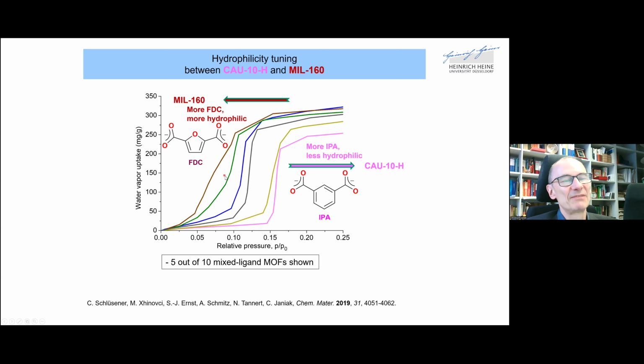Now if we partially replace furan dicarboxylate with isophthalate, we become a little bit more hydrophobic, and from the other direction we become a little bit more hydrophilic. These are 5 out of 10 modifications we have done with the mixed linker unit, and thereby this water uptake range can be adjusted. It may seem like a little game and not really so relevant, but for the technological application, such fine-tuning is actually more relevant than one thinks. But that would be an engineering issue. I will touch briefly upon that following.